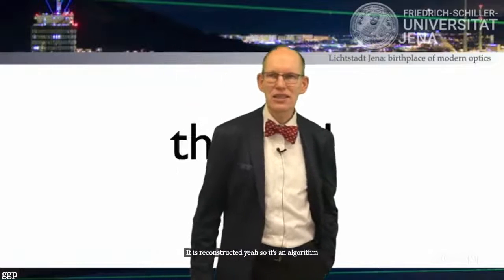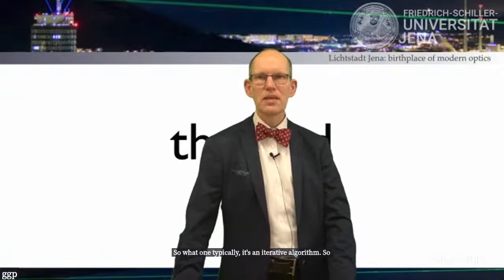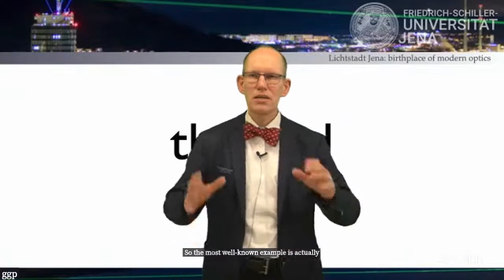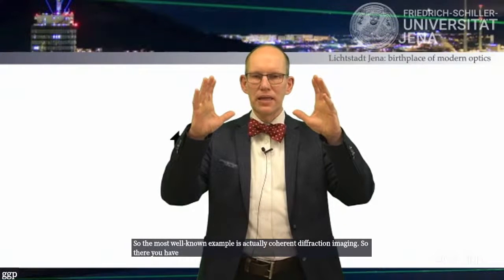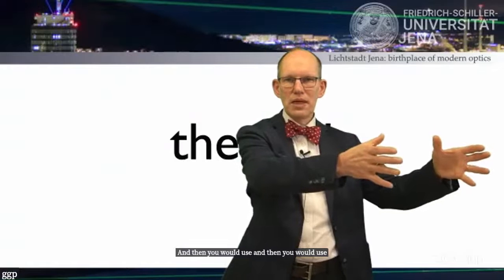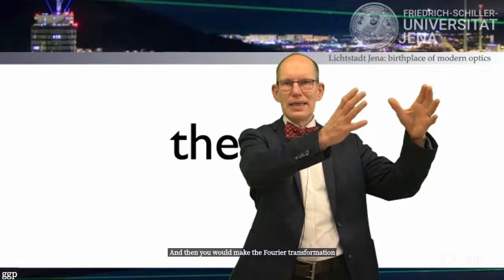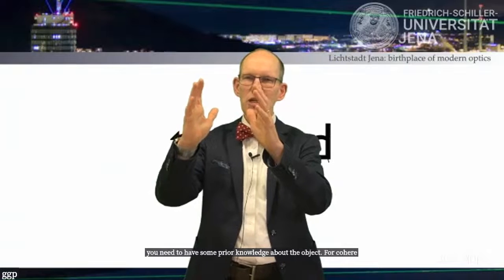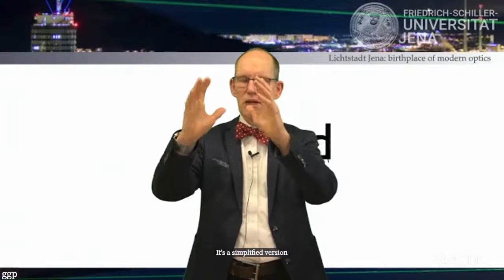It is reconstructed. It's an algorithm that reconstructs the phase. It's an iterative algorithm. The most well-known example is actually coherent diffraction imaging. There you have the diffraction pattern, right? And then you just guess the phase, and then you make the Fourier transformation, right? And you need to have some prior knowledge about the object. Coherent diffraction imaging is a simplified version of ptychography, particularly easy.